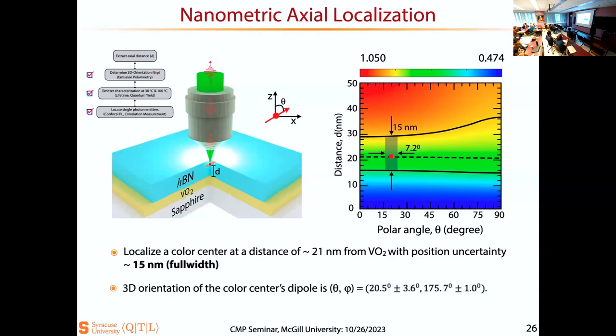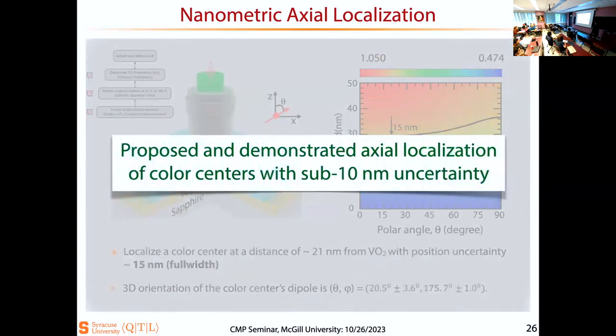So now we were really able to find out where the color center is, what the uncertainty in the polar angle is. This showed that we were able to locate the color center with a full width uncertainty of about 15 nanometers. So that was a truly nanoscopic localization of the color centers, plus the 3D orientation of the dipole moment. We extracted all the parameters in this. So we proposed and experimentally demonstrated a method of localizing it.